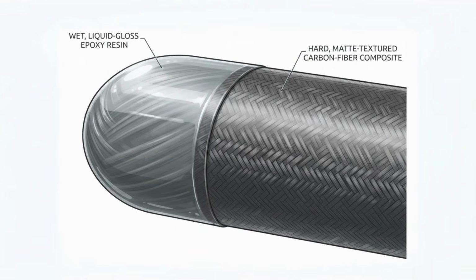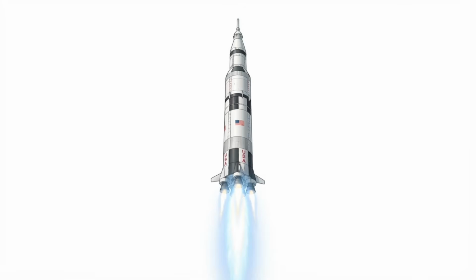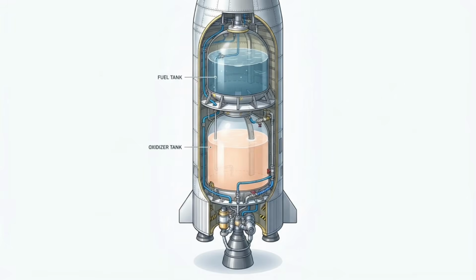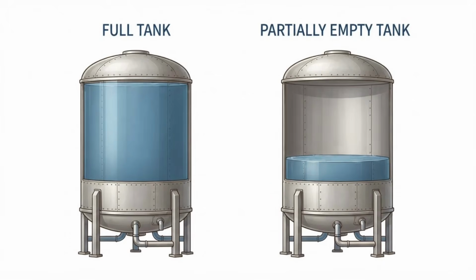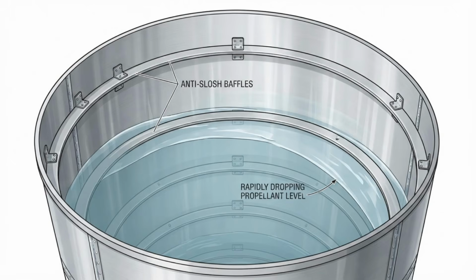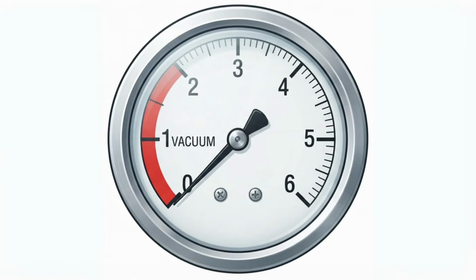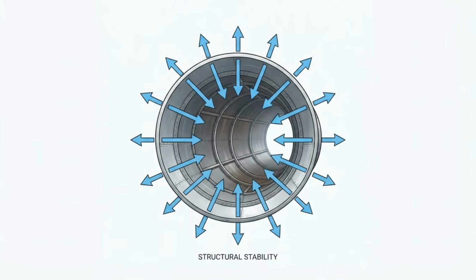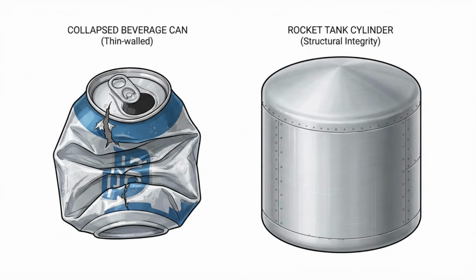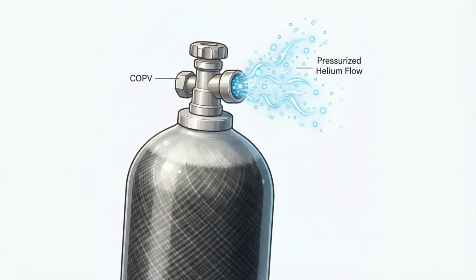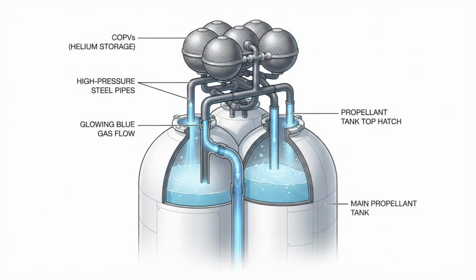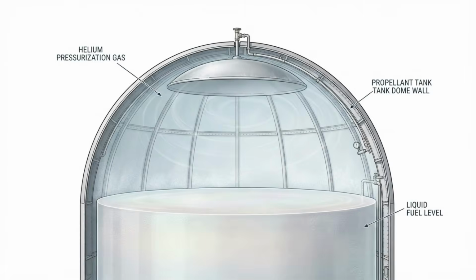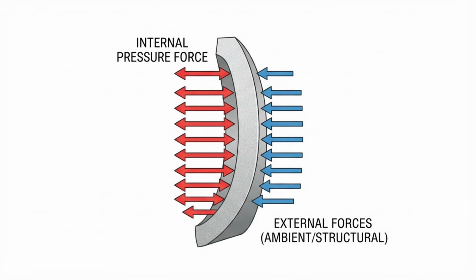The tank is then baked in an enormous industrial oven called an autoclave, curing the resin into a rigid, impenetrable shell. During flight, as the main engines consume the liquid fuel and oxidizer, the fluid levels in the main tanks rapidly drop, which would normally create a dangerous vacuum. To prevent the rocket from collapsing inward like an empty soda can, the highly pressurized helium from the COPVs is routed into the empty space of the propellant tanks, maintaining positive internal pressure and structural integrity.